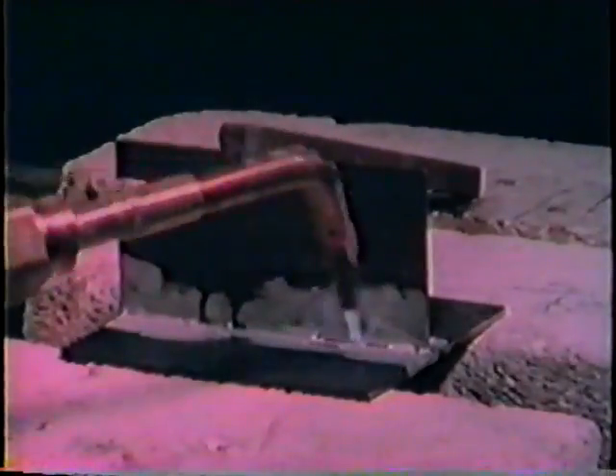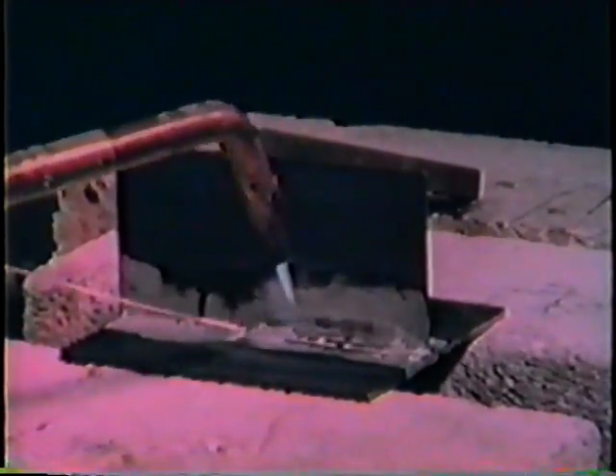Remember, if the alloy smokes, too much heat is being applied to the joint. Check to see that the distance between the face of the brazing head and the workpiece is at least 5/16 of an inch. Check also to see that the torch flame has remained in its slightly carburized position. Make sure that the alloy completely penetrates the joint.